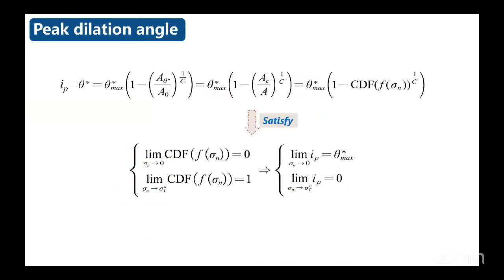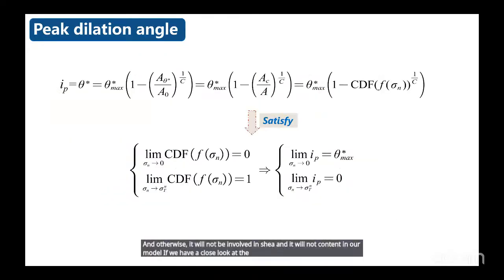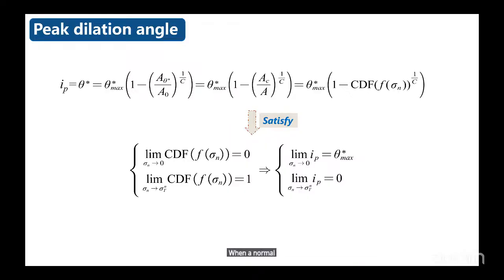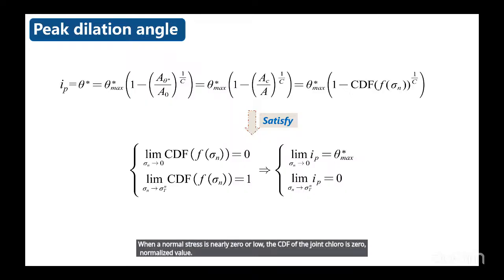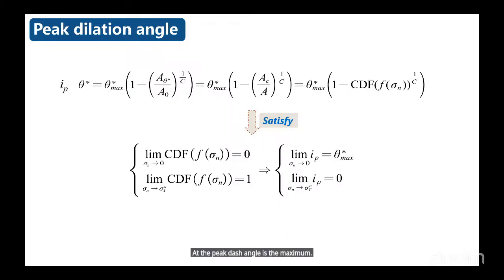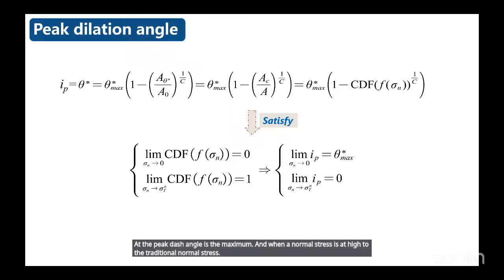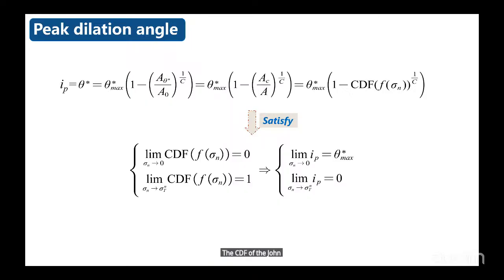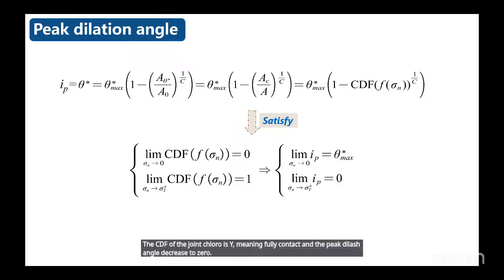If we have a close look at the equation for predicting the peak dilation angle, we found it also strictly follows the physical constraints. That is, when the normal stress is nearly 0 or very low, the CDF of the joint closure is 0, as a normalized value, and the peak dilation angle is at its maximum. And when the normal stress is as high as the transitional normal stress, the CDF of the joint closure is 1, meaning full contact, and the peak dilation angle decreases to 0.